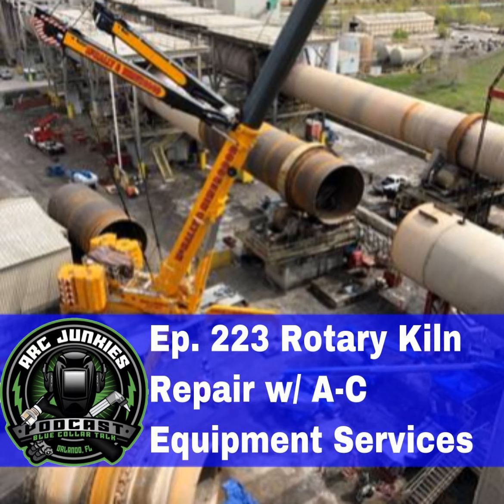That is common. It's not as exaggerated as you think, but we'll see a lot of shell deformation in kilns, and we analyze all the information we gather from a runout study to determine where a good place to cut it is, where you have maybe less than an inch of variation on the circumference of the shell. So when you are cutting into it, you can fit it up and end up with a relatively true pipe again. The heat is probably the biggest reason we replace shell. They're damaged due to losing the insulating refractory inside. They burn through kiln shell. It gets deformed. A lot of the heating and cooling cycles lead to failures in the steel, whether it's cracks from a weld or just brittleization of the steel itself.